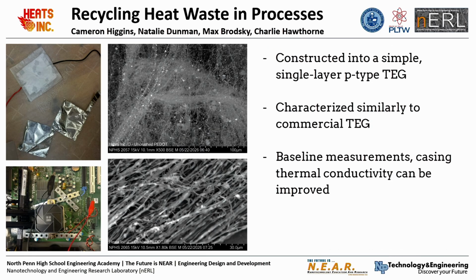We electrospun this solution into thin P-type thermoelectric nanofibers that, when a heat source is applied to them, drive positive charge carriers away from the source of that heat, generating a current. We characterized it very similarly to our commercial TEGs by measuring power and temperature statistics over a testing period. And these were really only meant to serve as baseline measurements, as there are many improvements that could be made to our simple construction of our TEG.